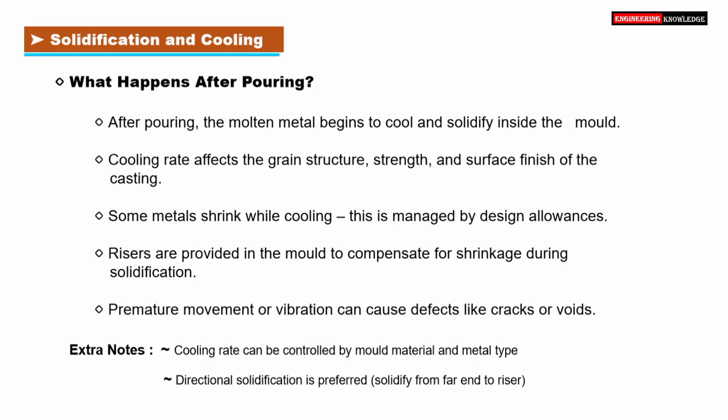If the casting is disturbed too early, it can lead to defects like cracks or internal voids. The cooling rate can be controlled by mold material and metal type. Directional solidification is preferred — the casting should solidify from the far end to the riser.